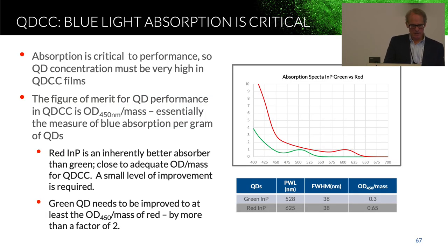If we look at cadmium-free quantum dots and we look at the absorption spectrum, a couple of things we'll notice. If you look at 450 on here, and I'm not sure I'm actually pointing at it because I can't really see the screen from here, you see that 450 is in a very unfortunate place. But unfortunately that's where the blue coordinate typically is, in this 450 to 460 range, so it happens to be at a local minimum in the absorption curve for green. And you can see that green is a considerably poorer absorber of light at 450 than red. And if we look at the OD per mass for typical green and typical red indium phosphide, all of this is cadmium-free material, we see that the numbers are 0.3 to 0.65. Remember, the numbers we were looking for are between 0.7 and 1.